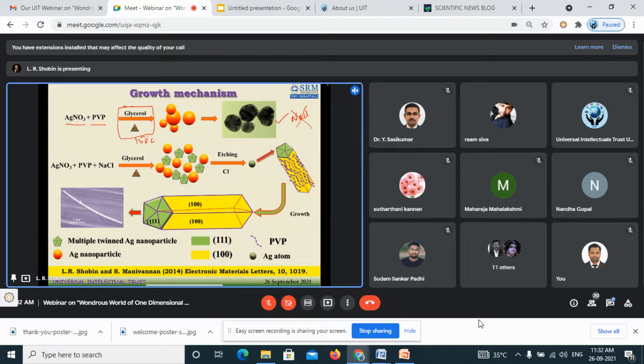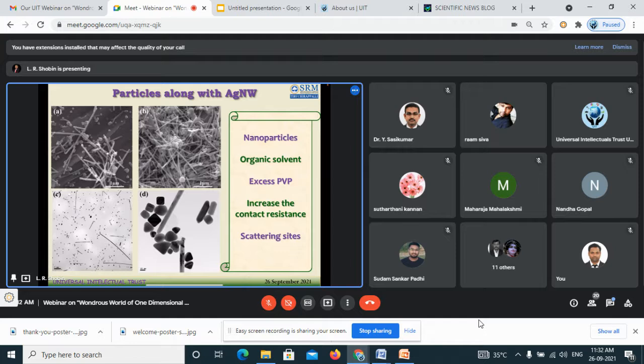But if you go for a small amount of NaCl, the etching will be produced, because this PVP will cap in this 100 plane. The PVP will be absorbed in the 100 plane because its affinity towards the 100 plane is high. So the 111 plane will be vacant actually. So the silver ions will come and sit over here, which will promote the growth in one direction, and which will give you the silver nanowires actually. Okay, so this is a possible growth mechanism.